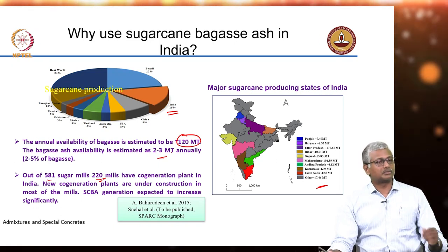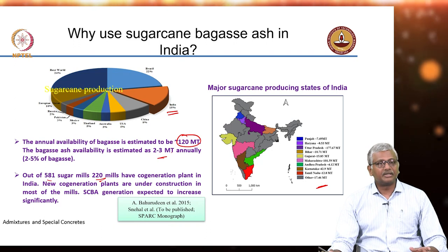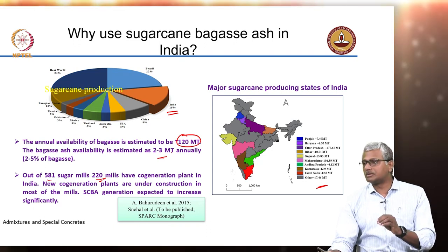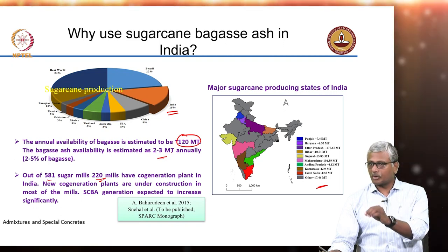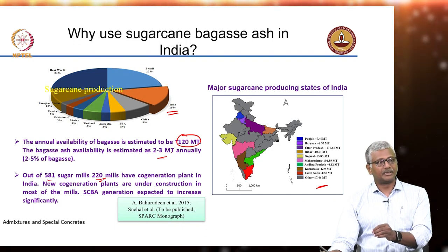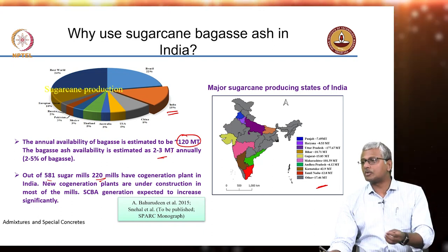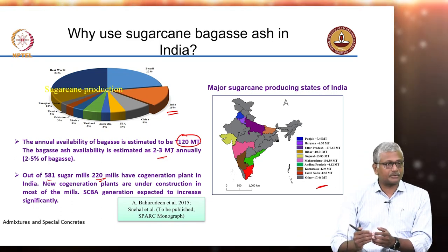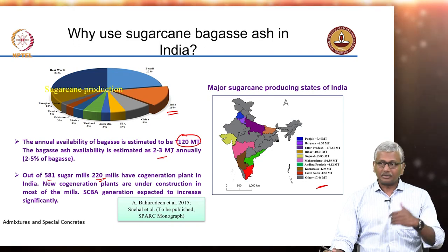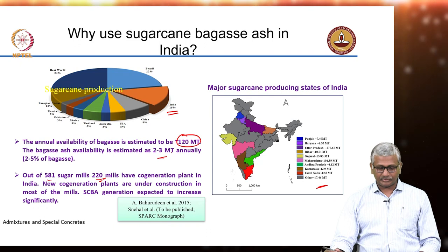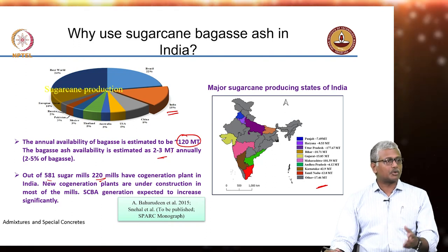This is nothing compared to fly ash — we are talking about 200 million tons for fly ash versus only 2-3 million tons here. But it starts making sense when we think about the location of sugar plants compared to thermal power plants, from the perspective of a ready-mix concrete or cement manufacturer. Trucking fly ash from a far-off distance may not be economical, but if a nearby sugar processing factory has bagasse ash, that could be a viable alternative for blended cement.